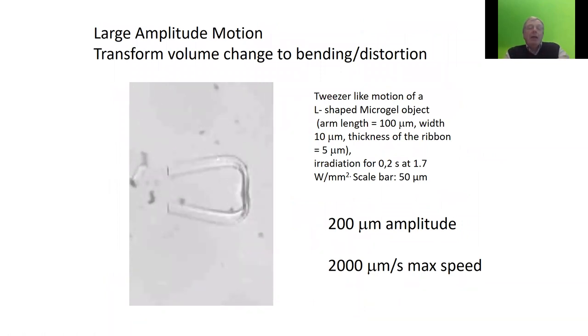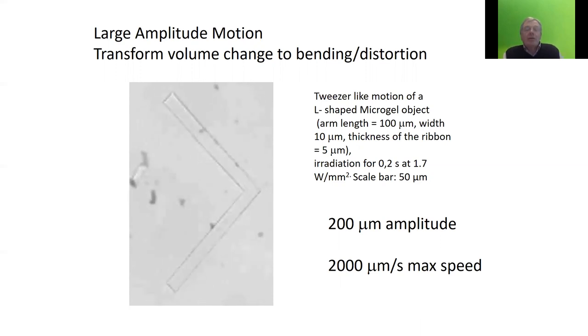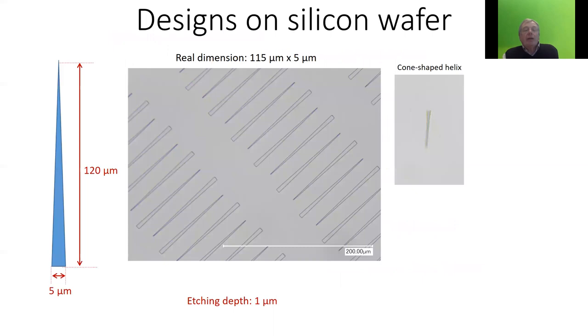When you take such an L-shaped hydrogel body and you heat it up very slowly, it just will shrink in its dimension, but it will keep its shape. If you now heat it up very quickly, it will be heated up quicker than the water can go out. And just in this simple geometry, you have parts where the water has a longer way to go out and parts where the water has a shorter way to go out. And this results in this heterogeneous deformation, which here is the nice tweezer action you see in the movie. And there, very fast, very large amplitudes can be created like this.